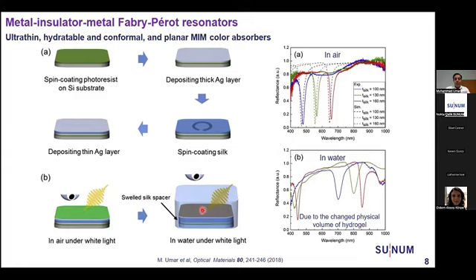And then if we put the same structure in water, the silk absorbs water from the environment and swells. So it changes the physical volume of the hydrogel, and the physical volume of the device as well. Therefore the resonance spectrum shifts to a higher wavelength, and this wavelength tuning is very high. So this means we can use this for biological sensing purposes.